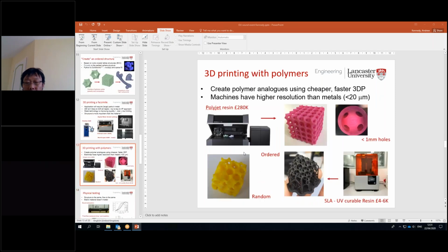So in fact, we could take other approaches, and we currently prefer the approach of 3D printing in polymers. I've said here we can create polymer analogs that are cheaper and faster. We've got some quite expensive machines, but actually some cheaper SLA machines produce very good results as well. Our better machines have much higher resolutions than metals, sub 20 microns.